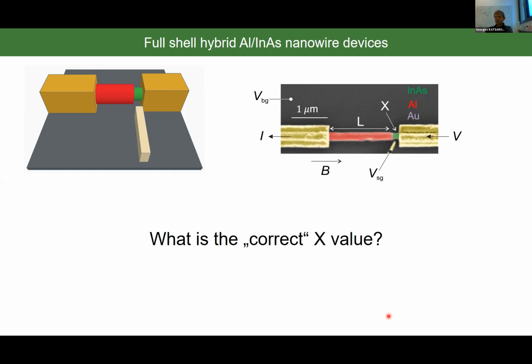So the conclusion after measuring roughly 40 devices is that if X is below 100 nanometers, the indium arsenide behaves like a tunnel barrier, while if X is above 100 nanometers, you form a quantum dot within the tunnel barrier. We call short junction devices the devices for which X is below 100 nanometers, and with that, I'm going to start showing you our results.